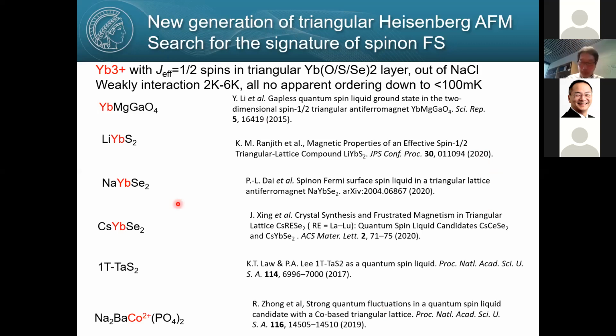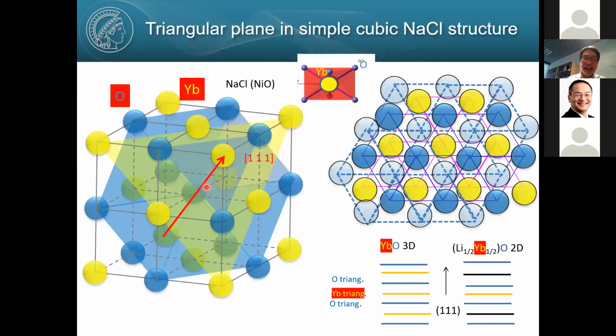They are made of ytterbium 3+, and the ground state is a J=1/2 doublet, equivalent to spin 1/2. But since they are f-electron systems, the interaction is much weaker, 2 to 6 K. Many of them don't show any apparent ordering down to very low temperature, below 100 millikelvin. And in those compounds, again, we have a stack of oxygen, ytterbium, and oxygen, as I mentioned, like this. This is an example of creating a triangular structure made of sodium chloride structure.